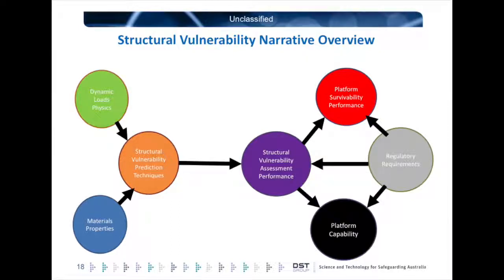So we have a lot of experience in the dynamic loads or shockwave loads physics area. We've also got people on site with a lot of experience in materials properties, performance of materials at high strain rates. And I should point out that compared with quasi-static strain rates and explosive loading, you can get strain rates of 10 to the 4 or 10 to the 5 per second. And at those loading rates, the properties of those materials can change quite dramatically in terms of their ultimate tensile strength, yield strength, and so forth.